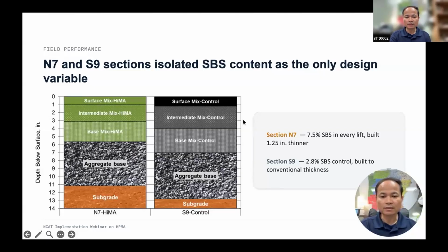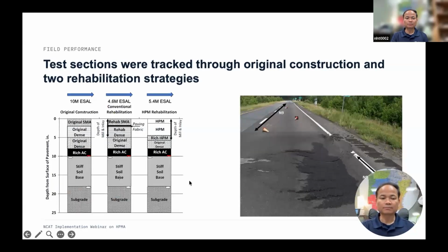You can see here another difference is that section N7 is using HiMA binder, and in this case it has about 7.5% SBS throughout the cross section, and then section S9 has a polymer modified surface and intermediate layer, but the base layer is unmodified asphalt. And then the base and the subgrade are the same.